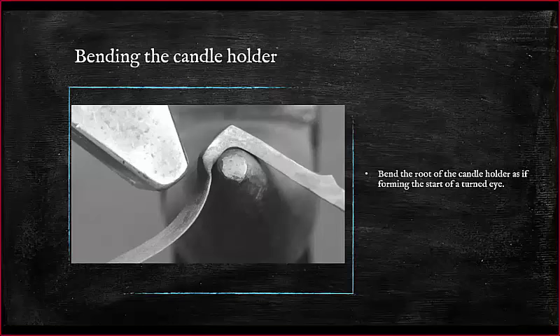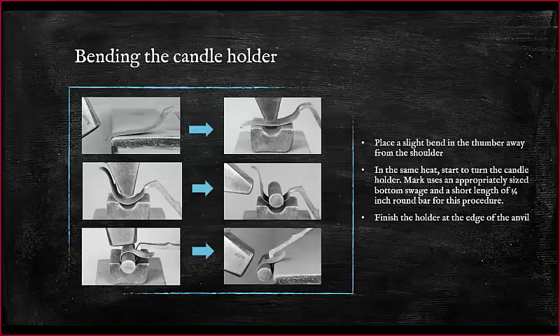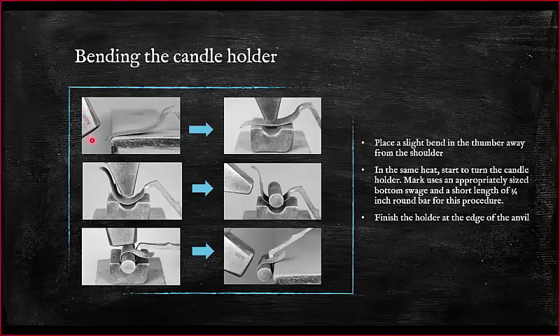So this is still corner number three. Now I can bend the eye. Because if I make corner number two, then I can't get in there to manipulate the stock for the eye. So again, the order is important. Bend corner number three, then start to turn the eye. And I'm turning the root of the candle holder over with my peen there. Can that be done in one heat? Probably, yes, it can. But the thin material, if it's not at a heat, then take the heat because it's going to be easy to crack this. You're showing that the peen of the hammer is hitting around this area of the candle holder. That's right. And I'm trying to make a bend there to kind of bring it back around this way.